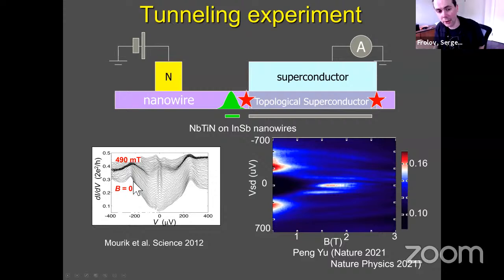Now, in the ideal scenario, there is absolutely nothing in the middle. And we have this background. And this is called a soft gap. When there is nothing, it's called hard gap. Now, soft gap is bad, but it's too naive to just say those words. You have to qualify them. There are 2 ways in which soft gap is bad. First way is it makes it absolutely terrible to make qubits. That's because all this signal here inside the gap, that's states. And these states can couple to your qubit states and make the decoherence very fast.